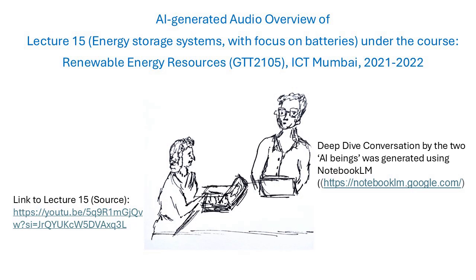Whittingham used lithium metal for the anode, but the cathode was titanium disulfide, TiS2, a layered material. And the big idea was intercalation. Lithium ions could slide into the layers of TiS2 during discharge and slide back out during charging, reversibly. That was the key to rechargeability, moving the ions in and out without wrecking the structure. You got about 2.5 volts, a solid-state concept, really.